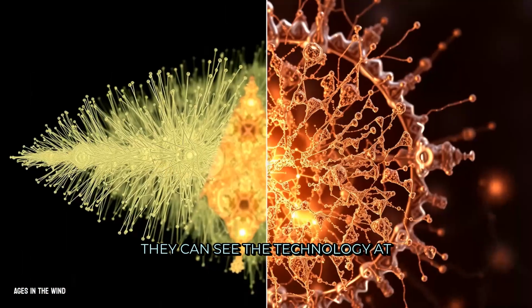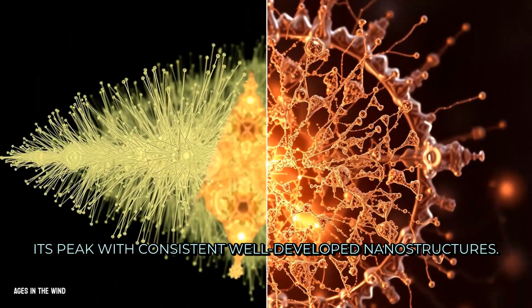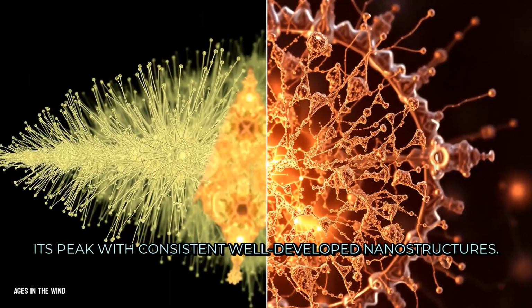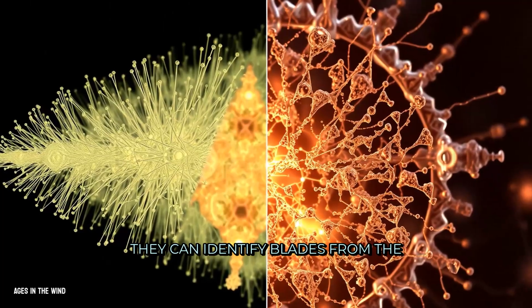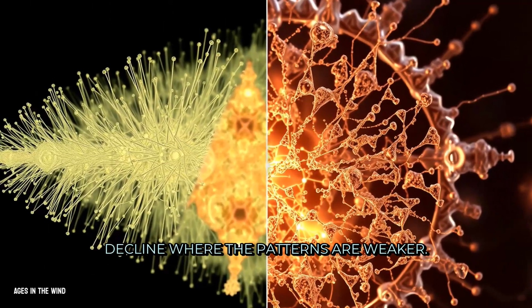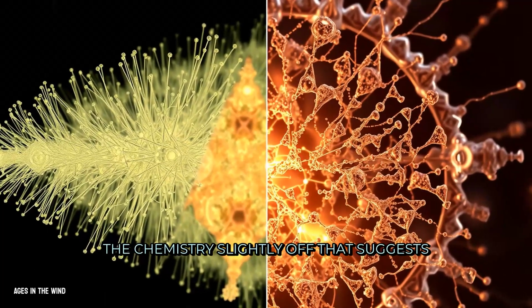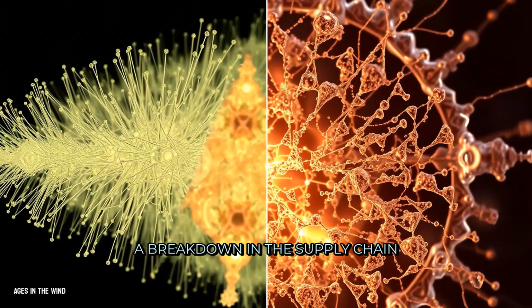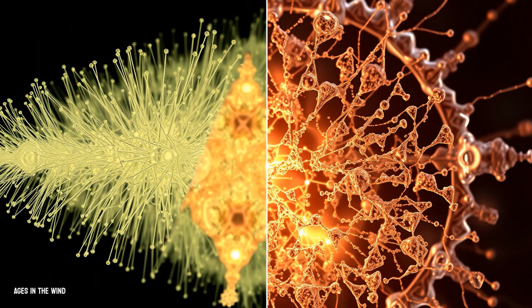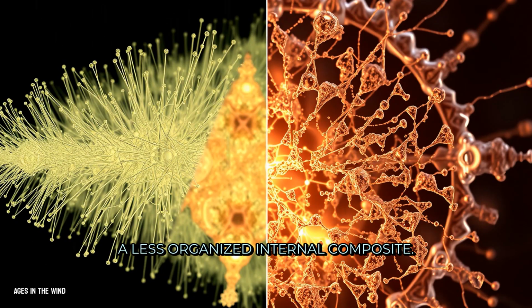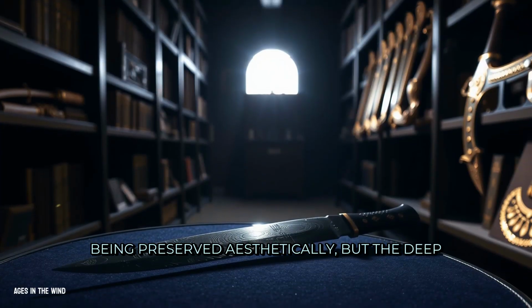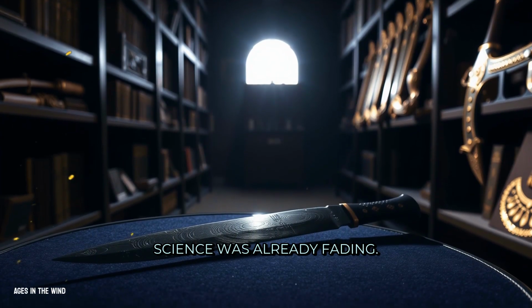They can see the technology at its peak with consistent, well-developed nanostructures. They can identify blades from the decline, where the patterns are weaker. The chemistry slightly off suggests a breakdown in the supply chain, or a loss of precise thermal knowledge. A blade from the 17th century might show a beautiful pattern but a less organized internal composite, a sign that the art was being preserved aesthetically, but the deep science was already fading.